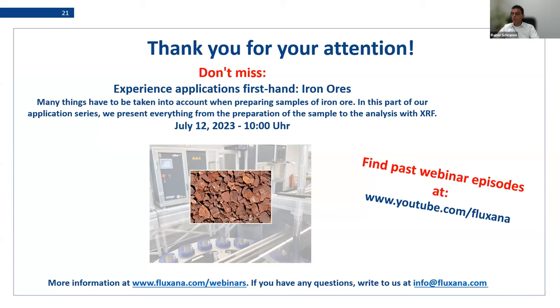If I have a sample with low Compton ratio, how can I increase it to 100%? So Compton ratio means Compton to Rayleigh ratio. If this is low, it means you have very little scattering, and then this kind of correction comes to a limit. So you have to see if the Compton scattering really is independent on your sample, on your element concentrations, and you have to try out if you can use it. Probably you can only find it out by testing it. For the Compton scattering, it's important that if the line is very close to the Compton line, it works very well. As far away the line is, as less it works. And if there's an absorption edge in between, this will also disturb the ratio. And in this way, it could be that it's not working anymore.